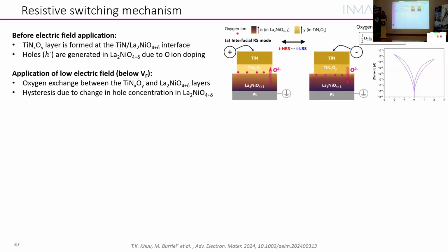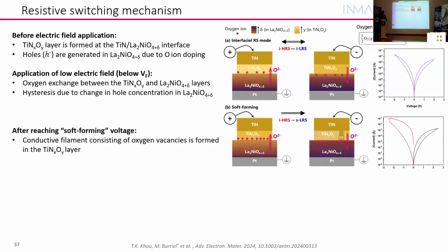Okay, so now I'm putting the 4 pieces of information together that we've got from the characterization, and we tried to develop a simplified model to see what is happening in our devices when we're doing the switching. So we believe that when we deposit titanium nitride, well, we believe and have observed that there's the titanium oxynitride layer that has formed and a gradient in the oxygen stoichiometry. If we only apply low voltage below the forming voltage, what we believe is happening is we have an oxygen exchange between the oxynitride and the lanthanum nickelate layer, and the hysteresis is due to the change in hole concentration of the lanthanum nickelate. That is in the first switching regime.